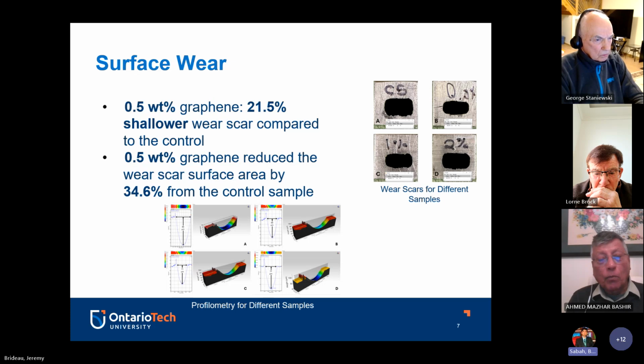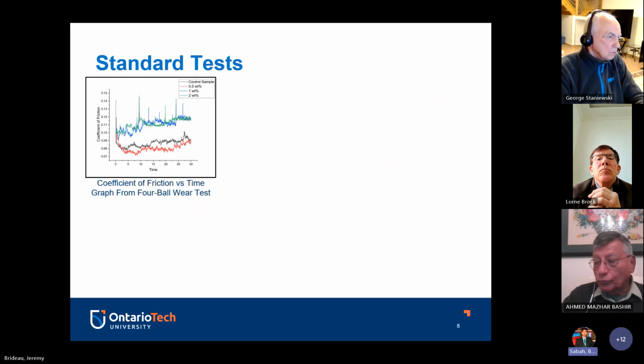So what we did was we contacted some of our industry partners, such as Petrolube in the United States. They're located in New Jersey, as well as Fluid Life here in Bradford, I believe, Ontario. And we were actually able to get some standardized test results. So we first started off with your meat and potatoes test, which is the four-ball wear test, to get the coefficient of friction. And as you can see, the 0.5 sample actually performed the best out of all of these. It had an average coefficient of 0.087, which is pretty good compared to the control sample, which was 0.091.